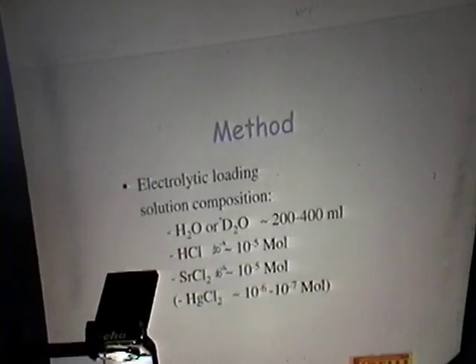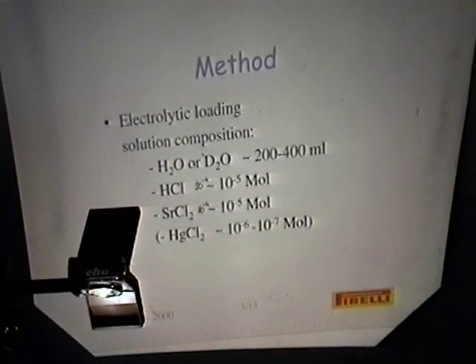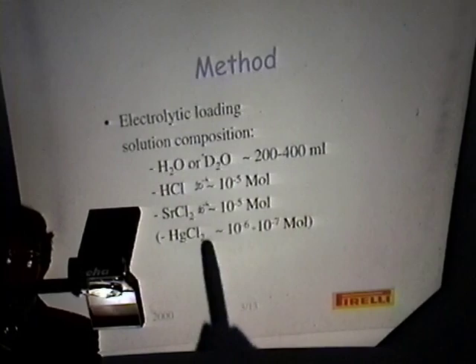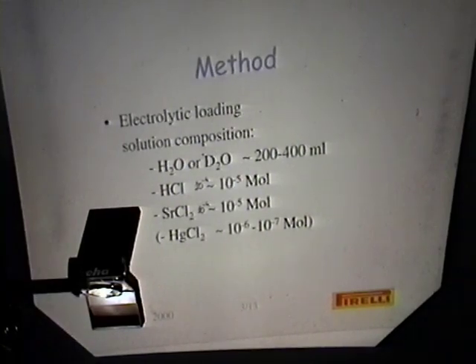I want only to make a few remarks about our experimental conditions. We used two different electrolytical cells, one with the volume of 200 milliliters, the other with volume of 400 milliliters. The solution was made with light distilled water or with the commercial heavy water, to which we added hydrochloric acid in a quantity of 10 to the minus 4 to 10 to the minus 5 moles. The same values for strontium chloride.